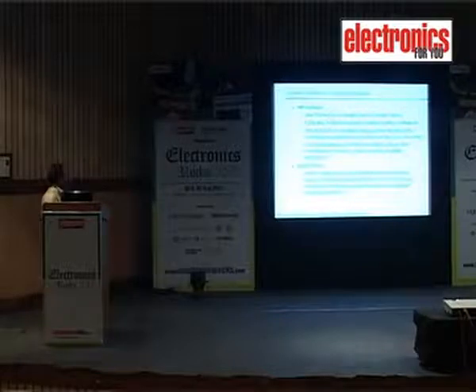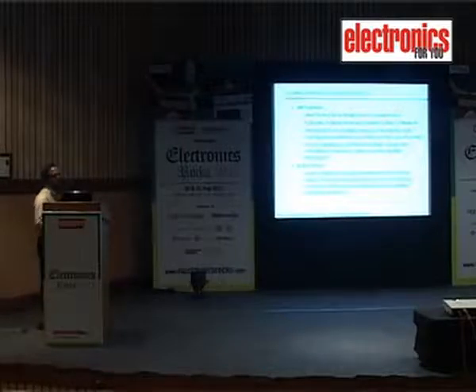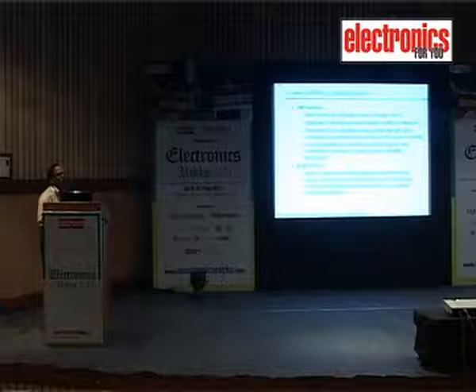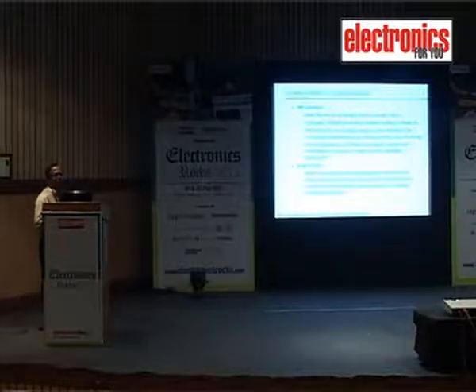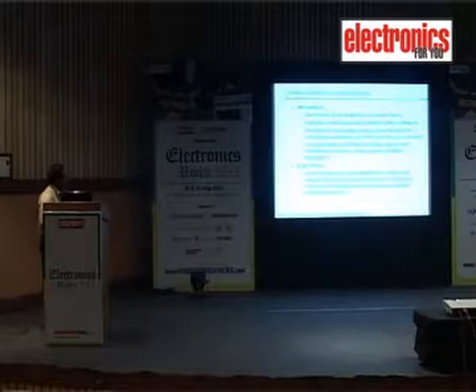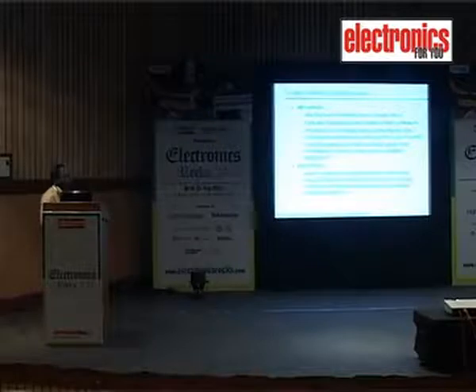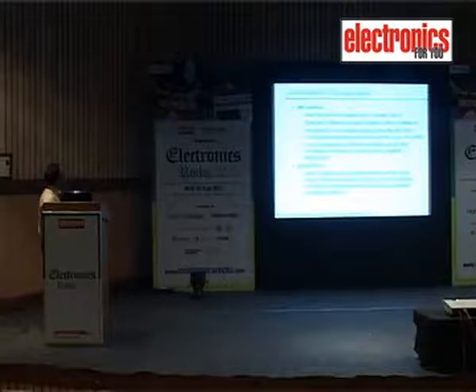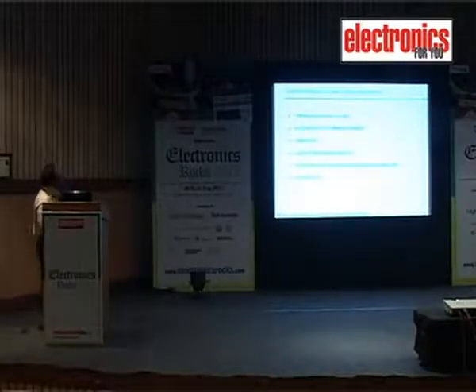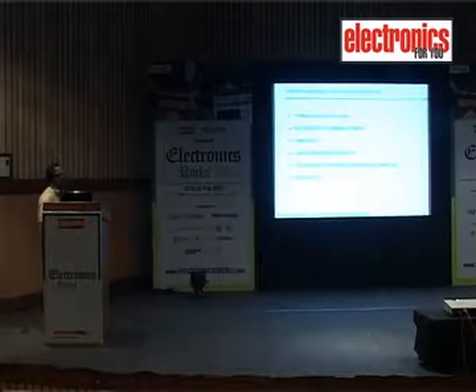And we also verify electrical integrity checks like intra-layer insulation and inter-layer insulation, because in multilayers, up to 14 layers are being qualified for space applications. We are making those PCBs in-house and they are being flown in spacecraft. So when we talk about very high layer counts, we have to be careful about intra-layer and inter-layer insulation resistance. Dielectric withstanding capability and interconnection resistance play an important role, and current carrying capacity is another important characteristic of the PCB.